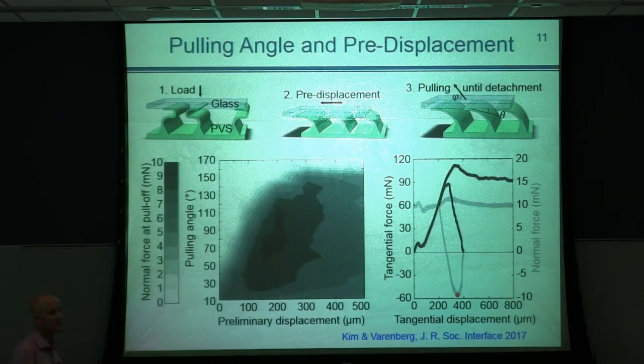And this is the summary of all the tests that we made to study the effect of pulling angle and preliminary displacement. So color here represents normal force, and it can be clearly seen that there is an optimum for the pulling angle and for the preliminary displacement, which suggests or proves that indeed the surfaces can be used in an adjustable way. So the pull-off force can be efficiently changed when pulling the surface in different directions. When angles are large, it detaches with zero force. When angles range within 70 to 100 degrees, then the force generated achieves maximum values.